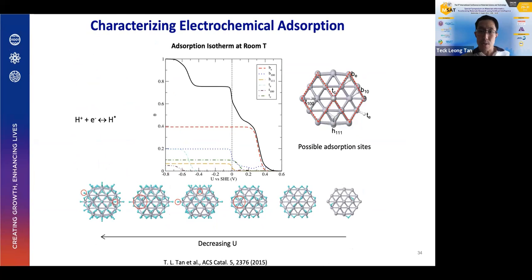Likewise, we can use this to study what we call adsorbate interactions. You can imagine that when we are doing, say, the hydrogen evolution reaction, the catalyst surface could be covered by different amounts of hydrogen. In the catalysis community, there's something called the adsorption isotherm. So we can use these models to study, for example, how the hydrogen adsorption, coverage and distribution change with electrode potential. The x-axis is the electrode potential. At very positive electrode potentials, there's not much hydrogen on the surface. But as the electrode potential gets more and more negative, more hydrogen comes to the surface. And from our modeling, we can identify which adsorption sites get covered first.